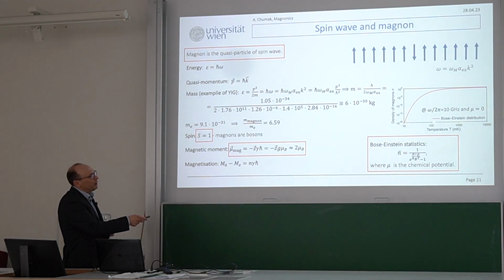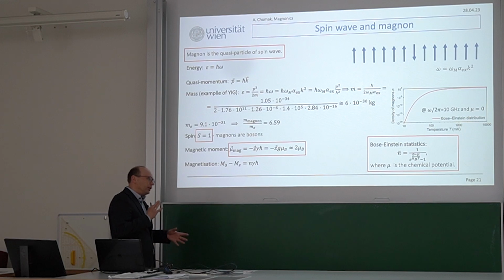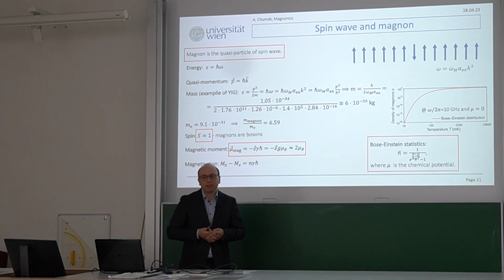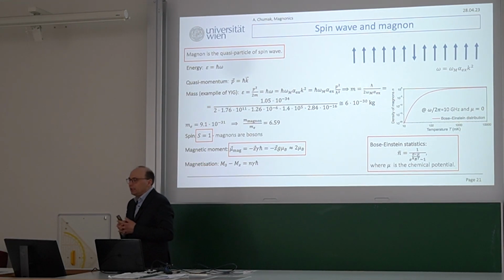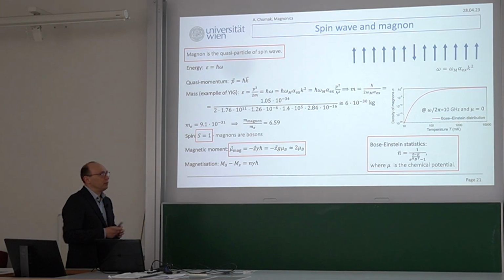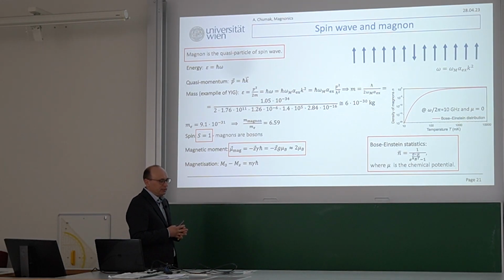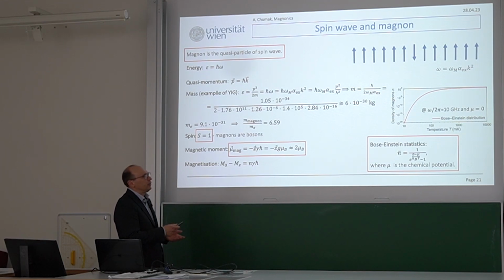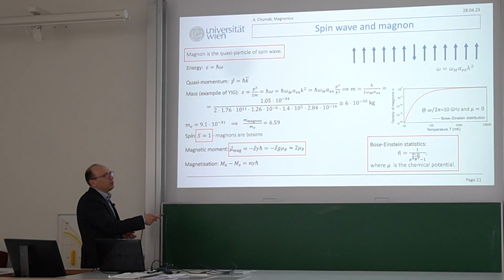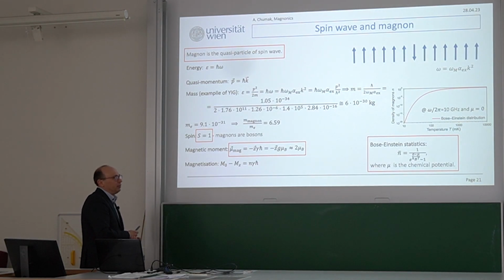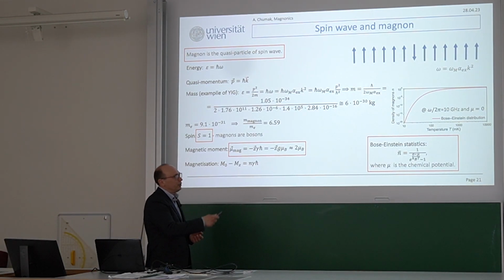If you go to 100 millikelvin, the probability will be 10 to the power minus 3. So it's already good. So principally, the system is already quite clean. At 100 millikelvin, you should be able to do quantum magnonics. If you go to 10 millikelvin, that's what people are doing nowadays. There are industrially available cryostats from Bluefors or Oxford Instruments, and then you go to 10 to the minus 20, the probability. That's why we need the system for quantum magnonics.